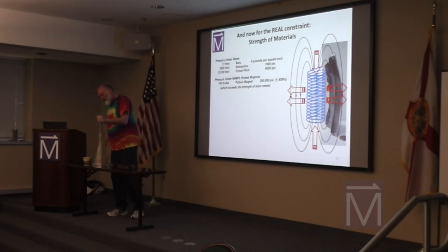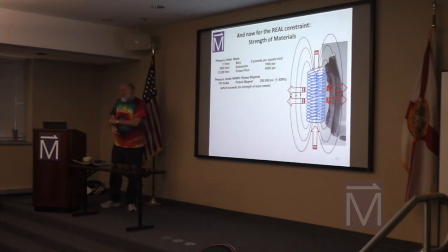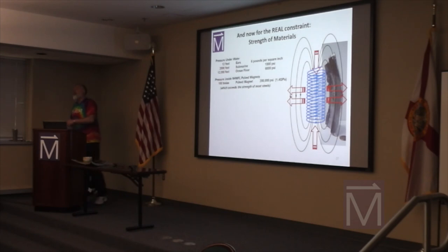They looked for places that nucleated the crack, and they couldn't find any. And ultimately, they did tests, and they had too much of those little crystals that are magnetic that make the steel brittle. So that research I told you about 15 minutes ago on steels is immediately relevant. It wasn't actually known that this was going to be such a big problem, and we didn't do the test before building the magnet. So we built the first 60 Tesla long pulse magnet in Los Alamos essentially out of glass. Glass is very strong, but it's also very brittle. The one that we have out there now, we tested, it's working very well. Actually, it has some problems, and we're repairing pieces of it as we upgrade the big pulse magnet.